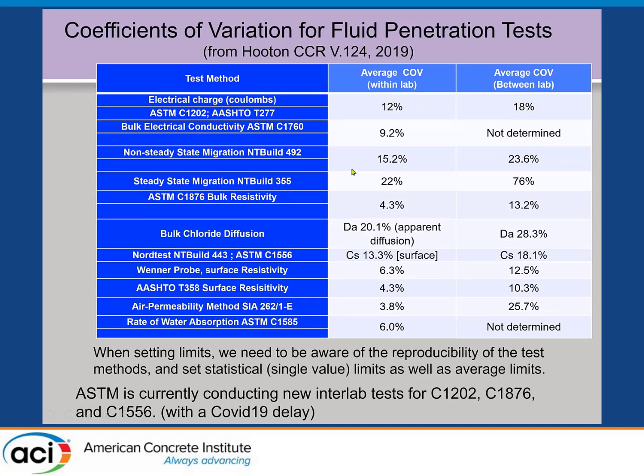these other test methods are in a similar range or worse, like the NT492 I just mentioned. The bulk resistivity method, 1556, is also more variable than that. And these resistivity tests are somewhat better, but we're actually ASTM's conducting interlab testing now. We're redoing the 1202 values, this new resistivity test, and we're going to redo the bulk diffusion test.